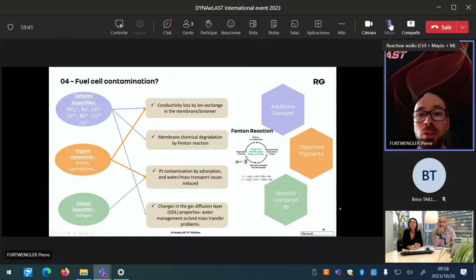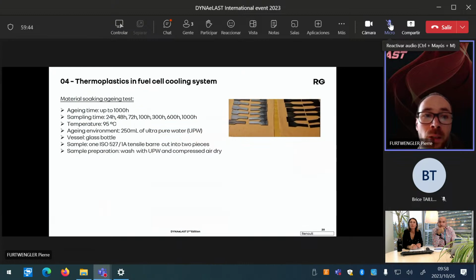In this specific idea, we started to initiate a protocol in Renault to try to investigate our materials. We share it with you because we don't know if it is the best one, so we are always waiting for feedback, and we are glad to share it if you think it is a good one also. You can use it. So we are taking samples to try to have always the same surface of exchange between the sample and the media, and our media is ultra pure water. We are using the ISO standard for traction, so the ISO 527 1A, we cut it in 2 pieces, and we put them in 250 milliliters of ultra pure water in a glass bottle with a cap, and the cap must have